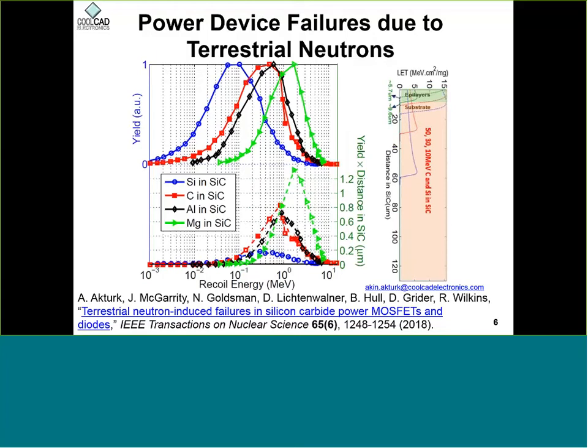In silicon, you can see it's roughly 1 MeV, and in carbon, you get a peak yield around maybe a few MeVs. But you also have some silicon and carbon primary knock-ons with higher energies as well. And you can have aluminum and magnesium. Aluminum can come from the interconnects, or those two things can also come from nuclear reactions with lattice atoms. And on the right, you can see how far these primary knock-ons can travel within a silicon carbide device.